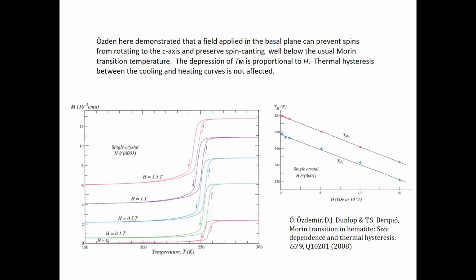And evidence in favor of this from Özdemir in this paper from 2008 is that by applying increasingly strong fields, you can depress the Morin transition. That is, you can hold the spins against their will in the basal plane below what should be the Morin transition. And the depression of the Morin transition is exactly proportional to the field. It's also interesting, this persistent thermal hysteresis in the cycling behavior of hematite across the transition. The width of the hysteresis is not affected by the field, so that seems to be intrinsic to the mineral.